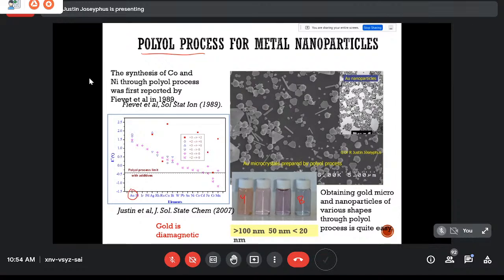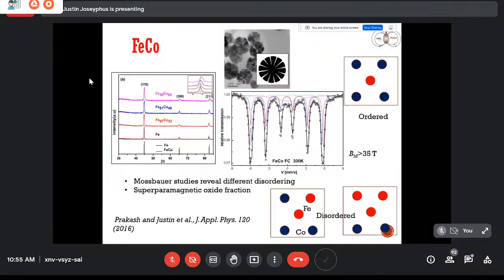So if you have a high, positive standard reduction potential, that implies you can prepare that using the polyol process. And if you see iron, this has a low standard reduction potential, but still we have prepared iron. So you see that this becomes the limit now, because so far the availability is only up to iron in the case of the polyol process. When you prepare iron, we can prepare other iron-based alloys also using the polyol process. So we tried to prepare iron cobalt and successfully prepared iron cobalt for the first time.